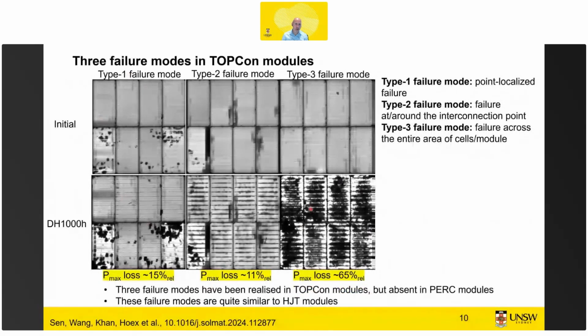Then for TOPCon, we only found 2, but the major concern was this, again, this type 3 failure, which was a failure over the whole sample. And these are EL images. I forgot to mention that. So dark means bad, bright means good. But yeah, we see that there are failure modes that really lead to very significant reductions.